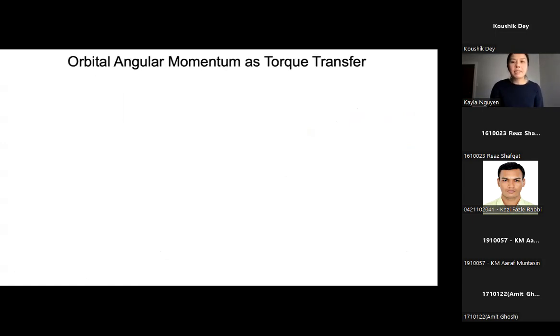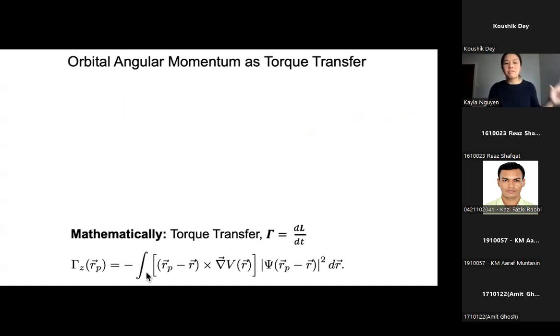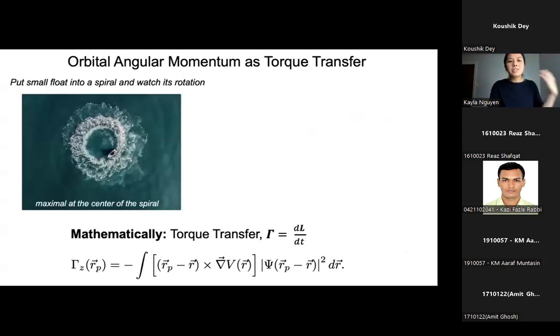Okay, this part of the talk will have one equation, which I will put here first. It's a technique that we developed to calculate torque transfer in our electron microscope. But I will also have a schematic to show what we're actually doing. Imagine your electron beam is a small boat or a small float in a spiral. What we can do is take our electron beam and watch it spiral within these polarization vortices, where we see that at the center of the spiral, we get the maximum signal.